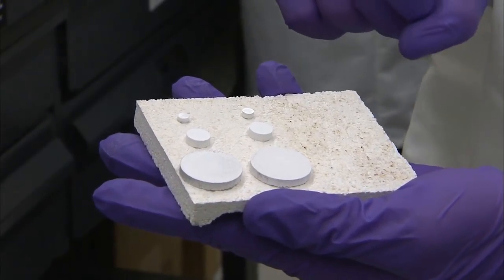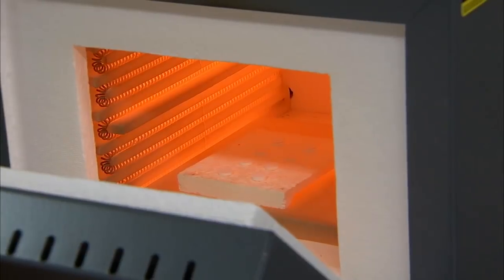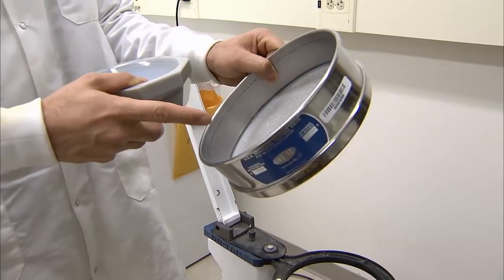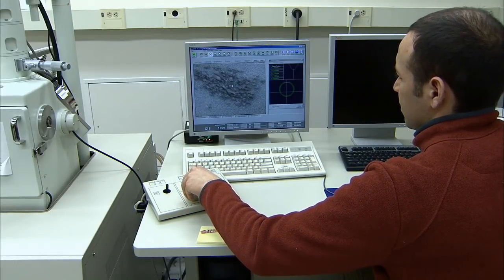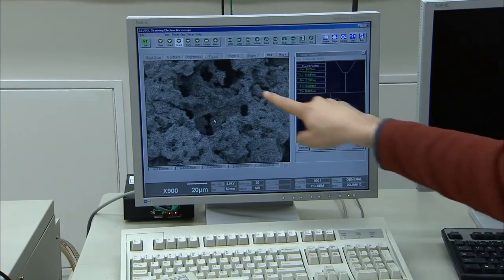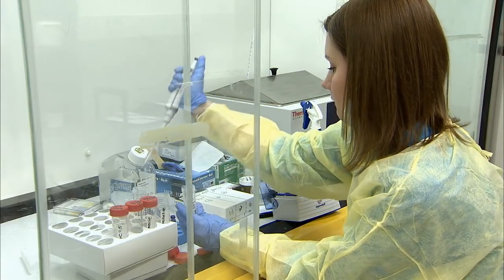We take the ceramic through many different stages. We prepare the ceramic in the lab starting with the raw materials — silica, calcium carbonate — mix them together and cook them in the furnace to make the bioceramic. After that, we take the material and grind it to a smaller particle size. We have different sieve meshes where we select particular particle sizes. When these particle sizes are selected, we analyze the particles using an electron microscope — a device that allows us to go to higher magnifications, normally like 20,000 magnifications of the grains, and then we can see the porous structures and the size of these pores. When we are happy with these porous particles, we can start using them for loading with drugs and then do the drug delivery applications.